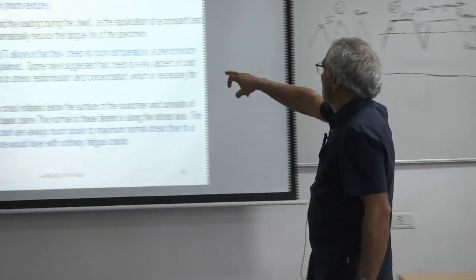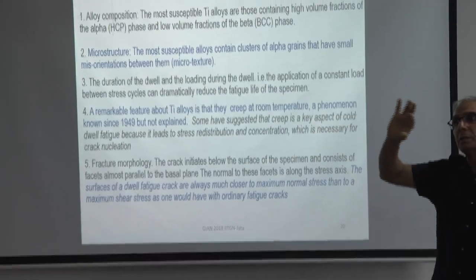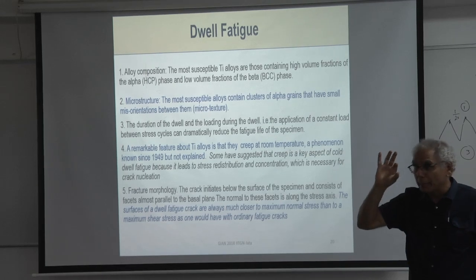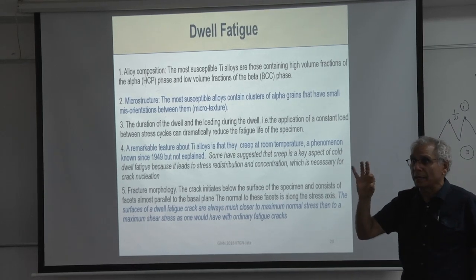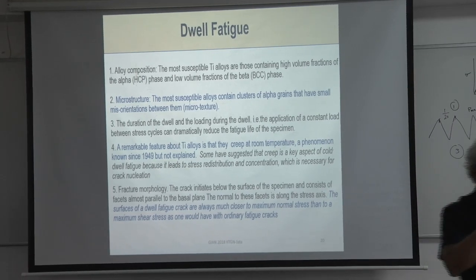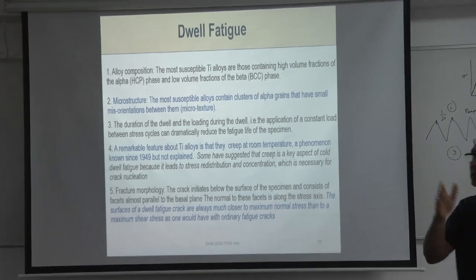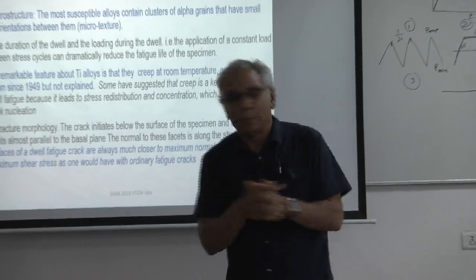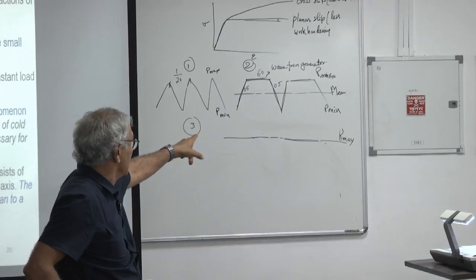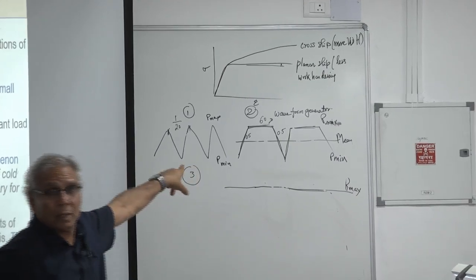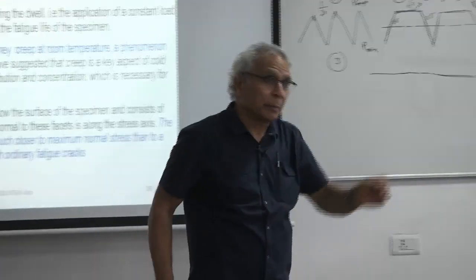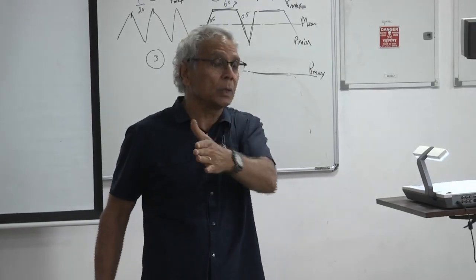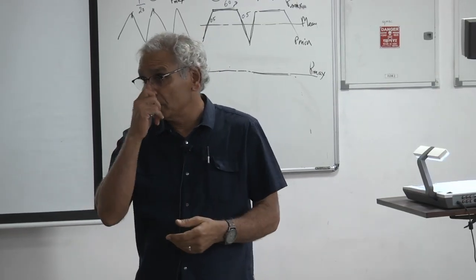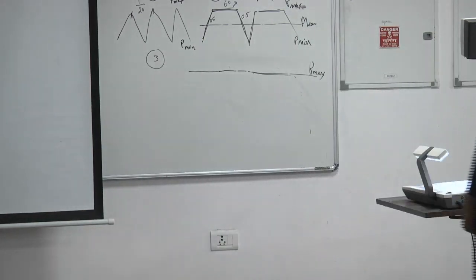And then the bottom line is this, that titanium alloys do creep at room temperature, but it's only primary strain, a very small amount of strain that happens at room temperature, or even at 120 degrees Celsius. So the question comes up: does it have a relationship with dwell fatigue? Because when you are holding the fatigue cycle for that 60 seconds at the hold time, will creep take place? Will that primary strain contribute to the overall fatigue life going down? That's the question that nobody knows how to answer, right?